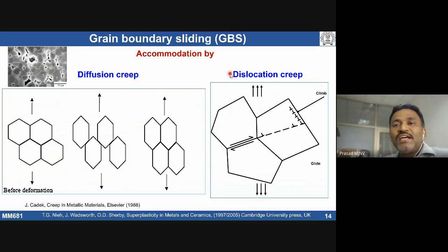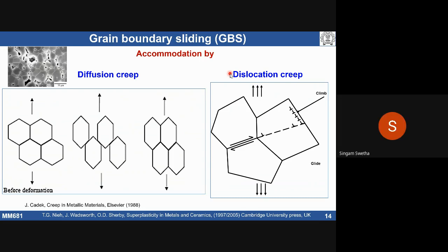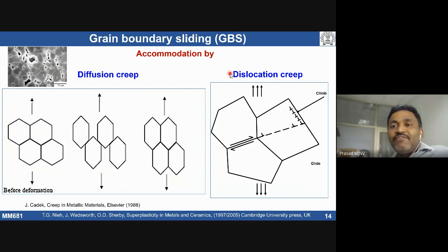What happens in the 0.3 times melting point case? In both the cases grain boundary sliding is there, but when you deform material at a temperature of 0.3 times the melting point, it is going to fail much earlier than the material deforming at 0.7 times the melting point. Why? What was the reason? I gave two temperatures, one 0.3 times the melting point, the other one a high temperature, 0.7 times the melting point. Maybe it's because of diffusion at high temperature. At high temperature, we have facilities for diffusion. Once there is diffusion, your cavity formation is going to be controlled. Mass transport can take place very easily by diffusion.